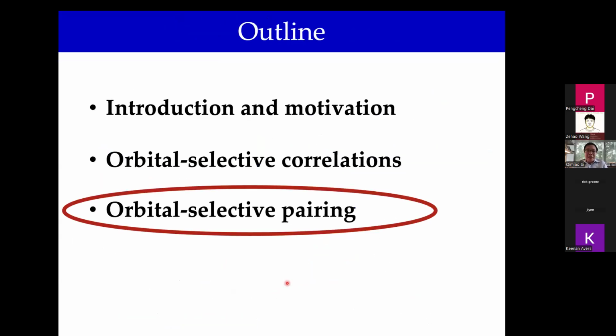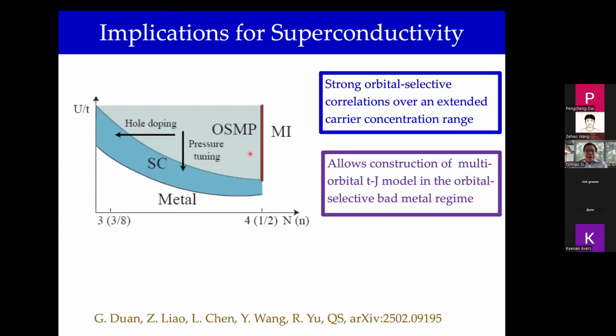I want to now transition into the consequences of these considerations for the pairing state. And so what we've done is, again, using a perspective that's anchored by this overall phase diagram, even though the system is metallic, it's a bad metal, but it's in proximity to this orbital-selective Mott regime. One can use this hypothetical orbital-selective Mott phase as a starting point, do pressure tuning, do doping variation, and presumably realize this superconducting part of the phase diagram.